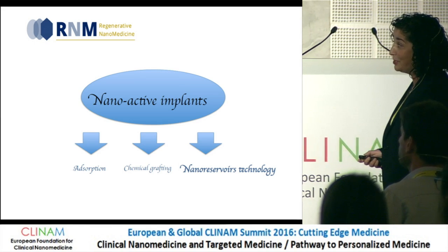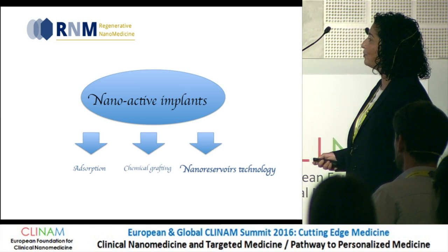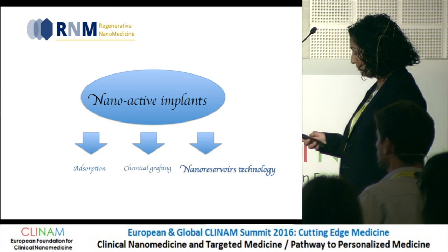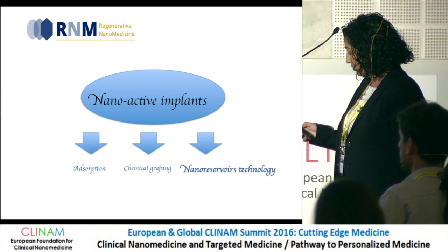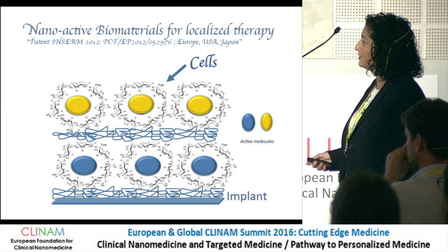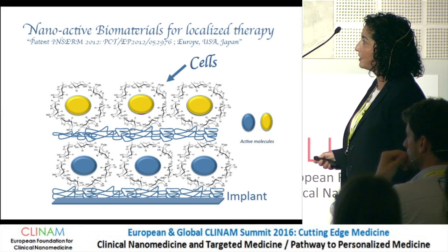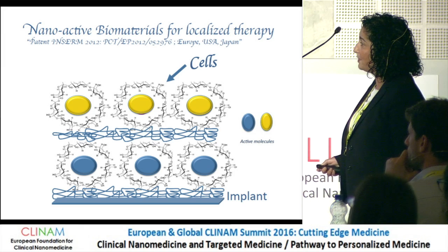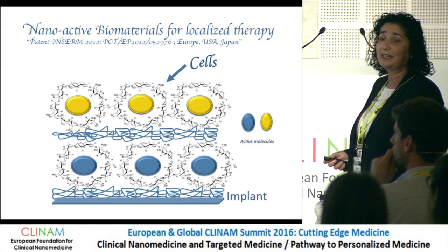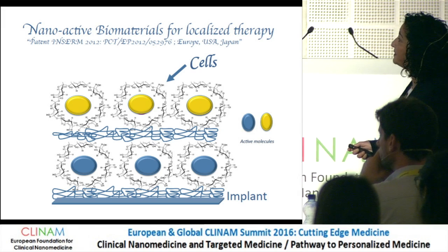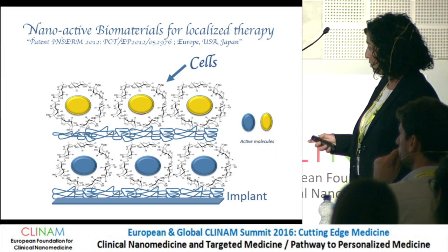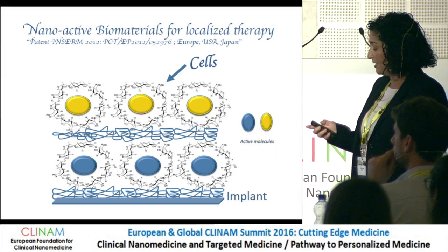We have click chemistry, but click chemistry is not yet ready for clinical application. In our laboratory, we have patented nanoreservoir technology. This alternates adsorption of oppositely charged molecules like polypeptides or polysaccharides. We can build step-by-step this nanostructured coating on top of the implant and incorporate active molecules inside. The mechanism is cell contact-dependent release — cells interact with the coating, cause degradation, and capture the active molecules.